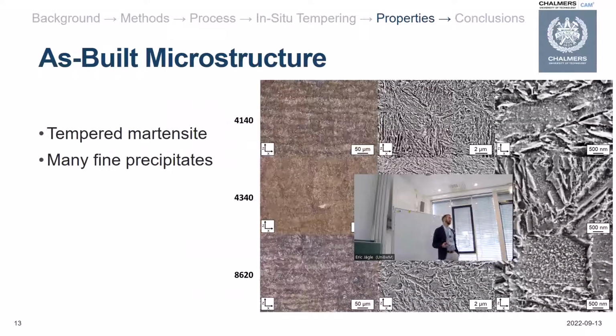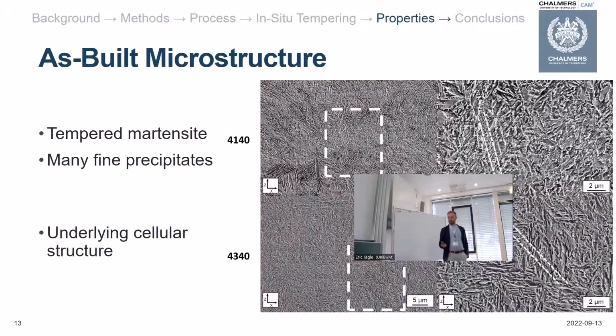One of the reasons why we're having this combination of high strength with decent ductility and toughness is, again, due to this tempered martensitic structure you have. We have very fine precipitates that are related to carbides within your material. So it's this sort of combination of properties that is part of the reason why you're getting this nice balance between the two. You do also have a hard to see but underlying cellular structure, which also has been shown to provide strengthening effects in other alloys, specifically 316L.